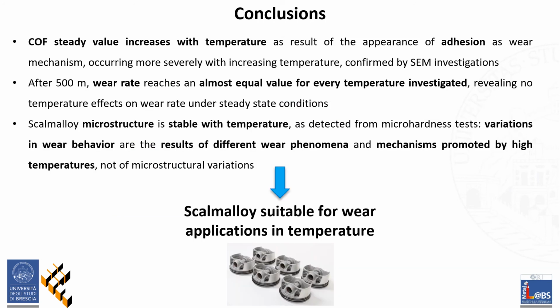So, from this study focused on the high temperature wear behavior of Scalmalloy, it emerged that first, coefficient of friction steady value increases with temperature as a result of the appearance of adhesion as wear mechanism, occurring more severely with increasing temperature, as confirmed in SEM analysis. After 500 meters, wear rate reaches an almost equal value for every temperature investigated, revealing no temperature effects on wear rate under steady-state conditions.